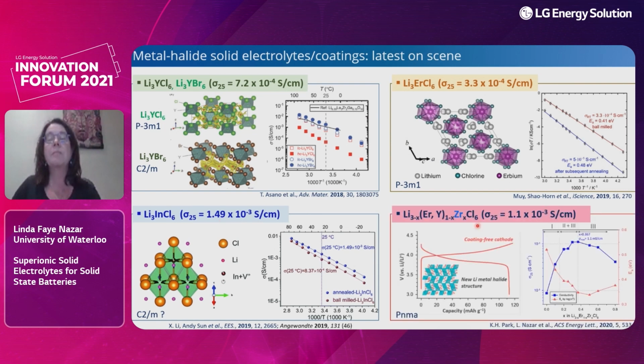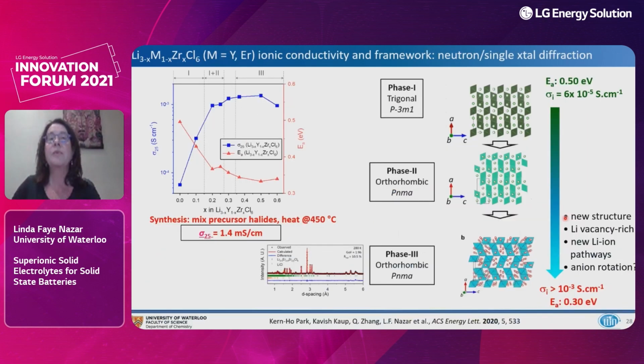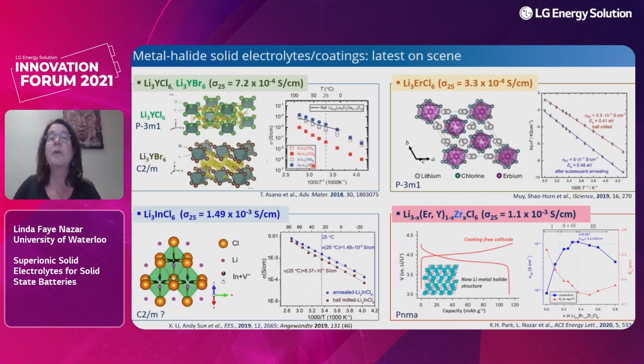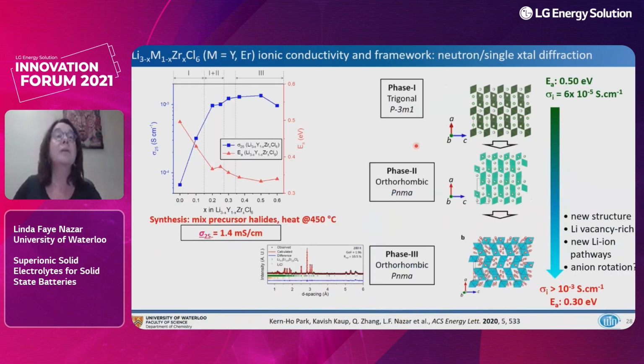And we followed up with a paper that described substitution of zirconium in the erbium-yttrium framework to again achieve this benchmark conductivity. And what is interesting about this substitution is that we're not simply increasing vacancy concentration or anything of the sort. We're actually making a new phase. So in phase 1, which is no zirconium substitution, in other words, lithium yttrium chloride, we have this low conductivity and fairly high activation energy.